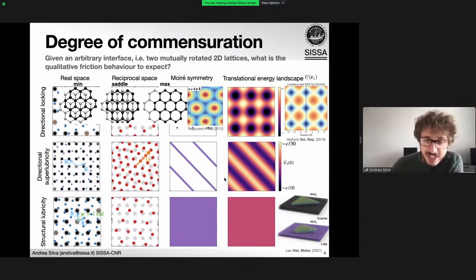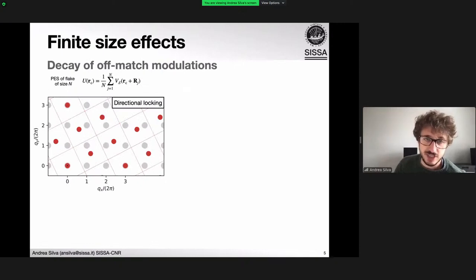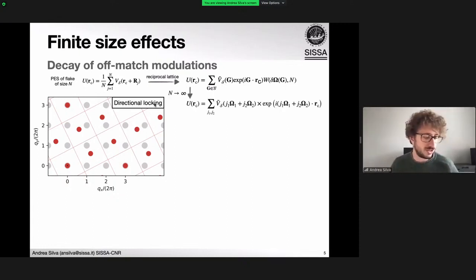As I said, the scaling law is kind of what defines structural lubricity, going from finite size, increasing the size, and the sublinear scaling. And we can describe that with this approach. So if we take a finite flake of size n, we can write the potential energy surface in real space by summing over the particles, or using the reciprocal lattice depicted down here. So we can expand in the Fourier components. And this is for a finite size flake that will go back to the one I showed you before for an infinite system.